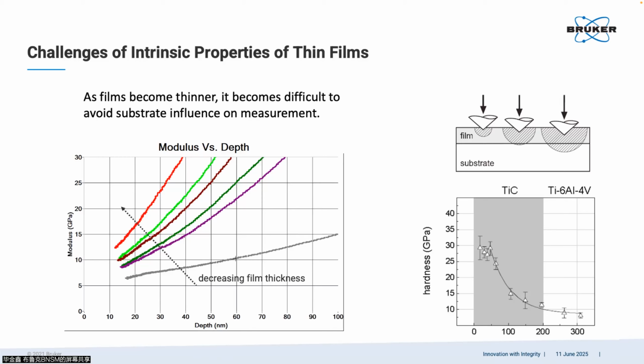So you can see these two very typical examples. If you're looking at hardness changing with indentation depth, if your top layer has a higher hardness compared to your substrate, then as you go deeper and deeper, you will find your hardness is decreasing. And this is the opposite case. If you look at modulus changing with depth and you have this behavior, that means your top layer has a smaller modulus compared with the substrate.